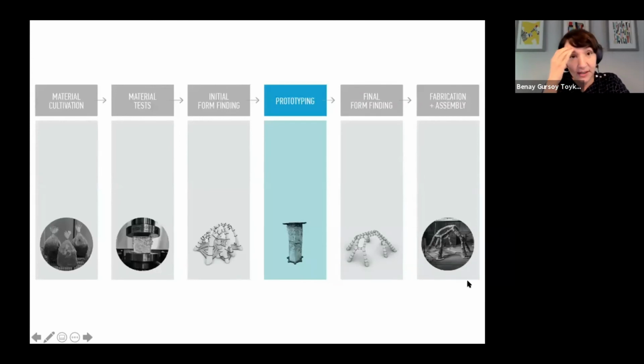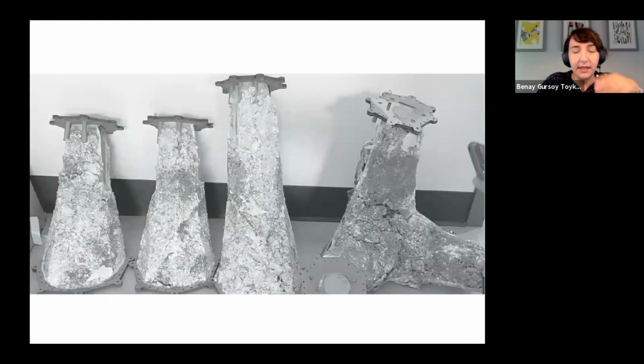After that, we started making several prototypes just to test mycelium growth and make some changes in the formwork design. We faced several challenges because the scale of these was pretty big, and we kept updating the formwork design. First we were using chipboard as material for the end plates, as you can see over here. Mycelium growth was okay, but we had gaps towards the end parts, and some cracks in the joints.